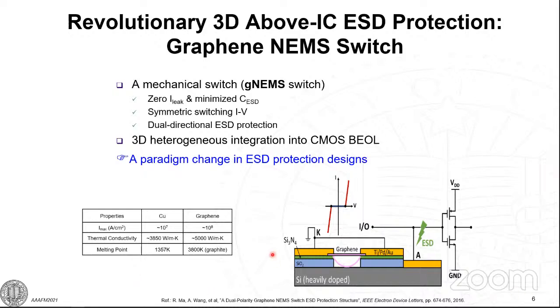Now the first one is the switch illustrated over here. Basically, there is a cavity over here. We have a graphene membrane on top of the cavity serving as one terminal, and the bottom silicon will be the second terminal. The two terminal device can be connected to the integrated circuit at the signal pad or the bias pad. So as an incoming ESD pulse comes in, the graphene membrane will start to be pulled down until it touches the bottom one. So the open structure will become a short circuit, and then it starts to discharge the static charge. This is how it works. Ideally, this can be symmetrical, but the structure in the prototype is not symmetrical, so you will see the measured data is slightly asymmetrical.